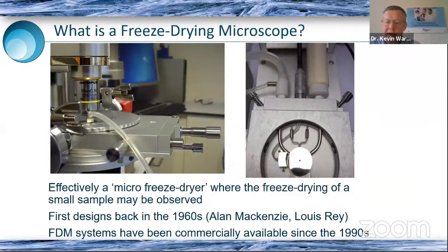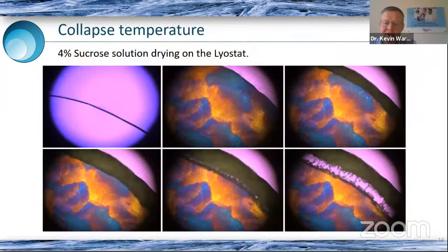But it was only really when we came up with our Lyostat 1, as we now call it, that things really became more readily available. And here's just a gallery of images that we can expect to see. This is a very simple example, sucrose, and many biological formulations are sucrose based, because sucrose is a non-reducing sugar, and we know that it can freeze dry very well. In fact, we know from some of the later studies that we've carried out using our micropress instrument, where we've looked at the mechanical properties, sucrose tends to have very good physical characteristics.